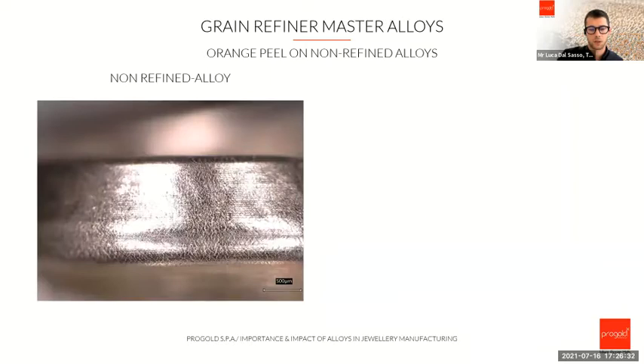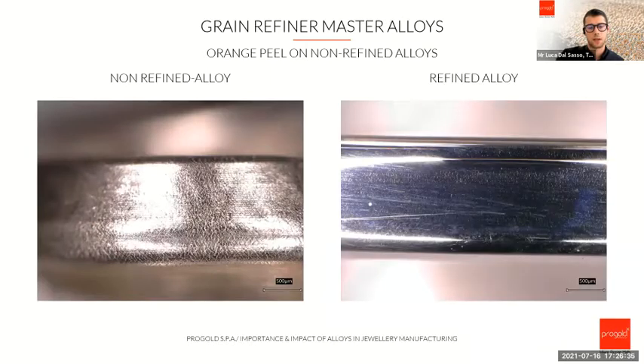Going on, this is a practical example of a difference between a non-refined master alloy and a refined one. So as you can see, once the piece is deformed, it shows all these defects under the lighting on the left side, and in the right one, we have really much less defect, a really smoother surface without all the problems we had in the other one. So this was the part of the presentation regarding the orange peel.